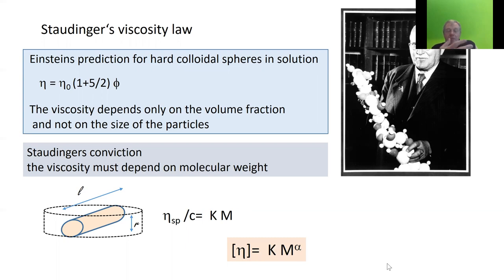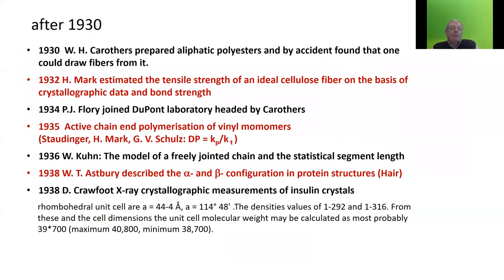Unfortunately wrong, we know nowadays, because we know that the macromolecules are not stiff, that there must be a scaling exponent alpha, which could be 0.5 to 0.8, depending on the quality of the solvent. It's remarkable that by this equation, he still could take his data, approximate them, and use them to prove that the macromolecules exist at that time. Again, you see some conviction in there. The molecules have to be stiff. So it was only in 1936 that W. Kuhn developed the model of the freely jointed chain and the statistical segment length. And Staudinger never liked this. That was not appropriate to him.